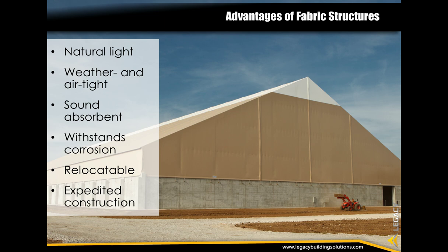Fabric cladding is installed up to 3 times faster than comparable steel sheeting. Most fabric buildings require 0.02 to 0.03 man-hours per square foot to be installed, compared to steel sheeting, which requires 0.04 to 0.07 man-hours per square foot. This allows the building owner to realize a faster ROI due to decreased construction time and associated costs.